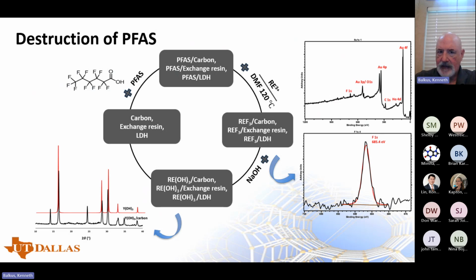So all you've got to do is take the carbon that now has the metal fluoride on it and heat it up with sodium hydroxide. And sure enough, all the metal fluoride gets converted to metal hydroxide. And once you have metal hydroxide, that can easily be redissolved under low pH and regenerate the rare earth ions. And I should point out that if you look at any of the adsorbents, there is no evidence of fluorine present at this stage. So all the fluorine's gone. Now, that doesn't mean that we've necessarily converted all that we adsorbed, but there's none left on the carbon after this reaction. So then what you end up with is your carbon regenerated,